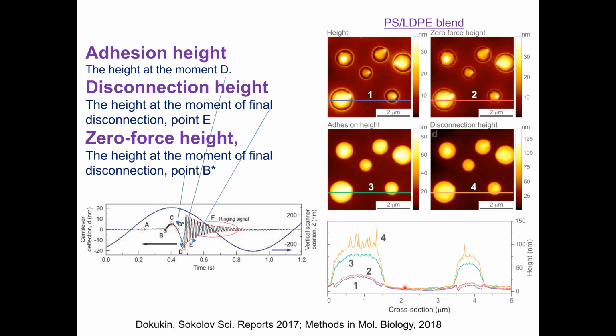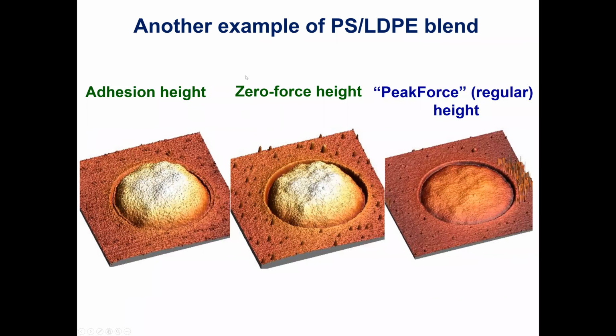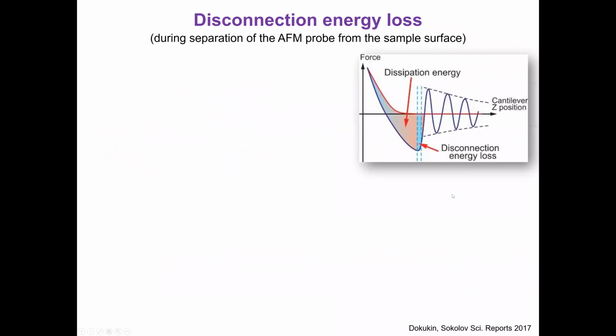And at the same time, if you look in the middle, it is polystyrene. It's pretty homogeneous, because it's pretty rigid and not a lot of deformation. Not a lot of these dangling bonds, which we pull using the AFM probe. So this is, again, in 3D, you can look at some of the pictures showing you the adhesion height, where you pull off this material, low density polyethylene, zero force looks like that, and the regular height looks kind of a little bit ironed out.